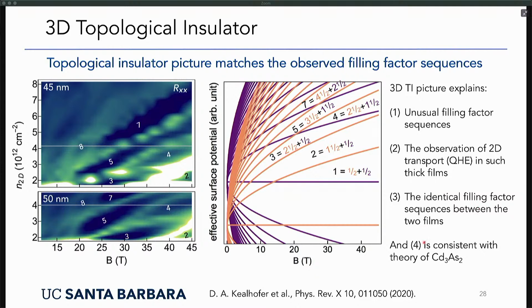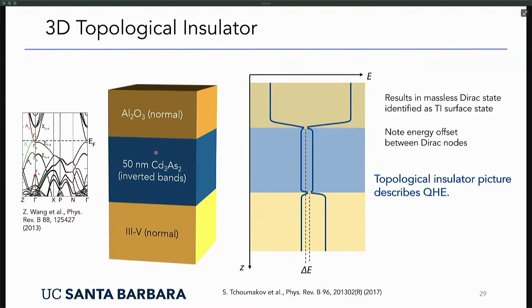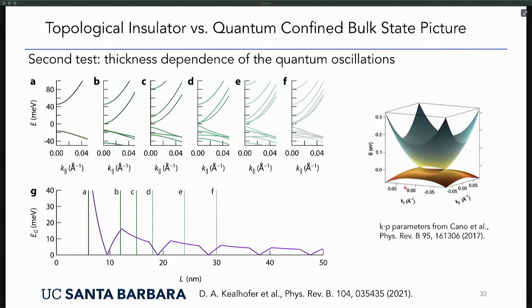And it's also consistent with the theory of cadmium arsenide. So the picture here is a slightly different way of showing this offset in the surface potential. We have these band crossings here. Blue is our cadmium arsenide that has inverted bands. We resolve this going to the normal materials such as aluminum oxide and the III-V. And it requires these Dirac fermions at the interfaces, but the interfaces are a little different, so we get this slight energy offset between them. So this topological insulator picture completely describes our quantum Hall effect.